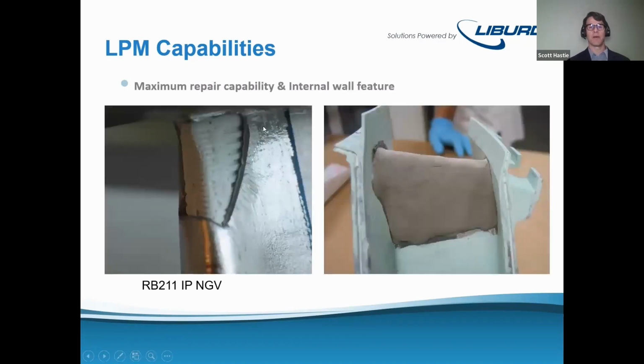And we said yes. The real key thing for this repair was there was a limitation that the repair had to have the internal wall feature. So typically on the external, it's pretty easy to do the machining so you can match the wall features of the external feature. But you can see here that there's some cooling fins along this surface and along the leading edge. And what we've done is we've cast a ceramic core, just like a new make casting process, and then we're able to press our LPM material around that leading edge, and then we've prepped up and around that, so we're building up the whole leading edge at the same time to execute this repair.